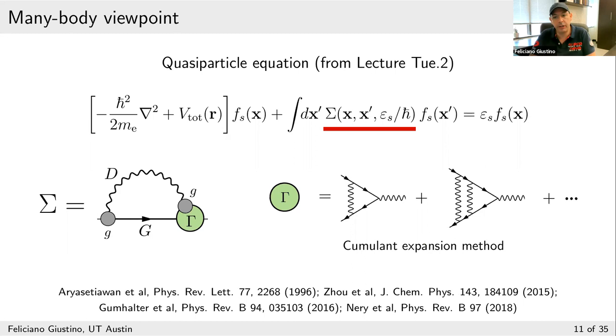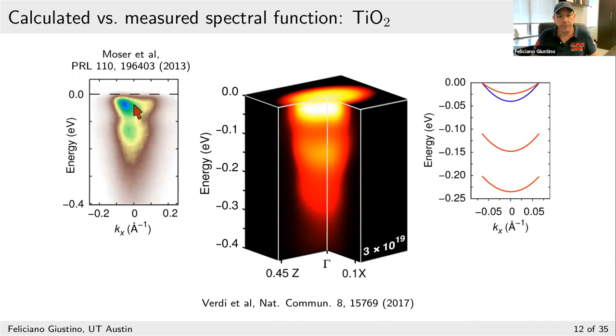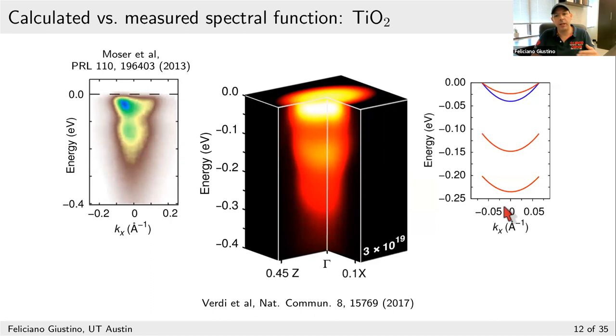Let me show what happens if you apply this methodology. Comparing the titanium dioxide experiment with a calculation performed by Carla Verdi, you see the first quasi-particle band, the first satellite, the second satellite. Tracking the maxima, you find the first red line (the quasi-particle band) and two satellites. The bottom line is that there is a way to be predictive and to perform calculations that are in reasonably good agreement with experiments.